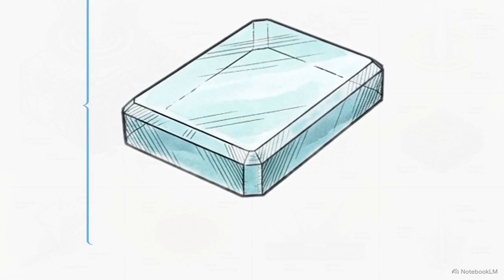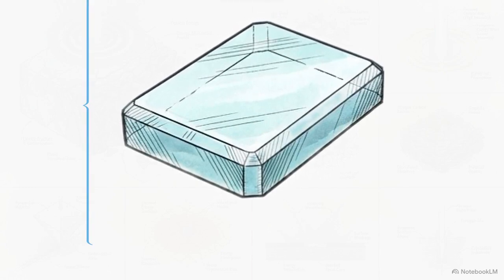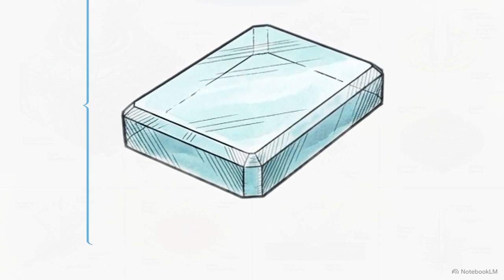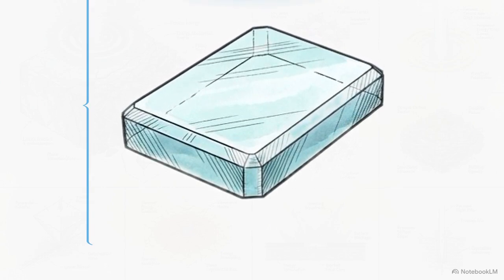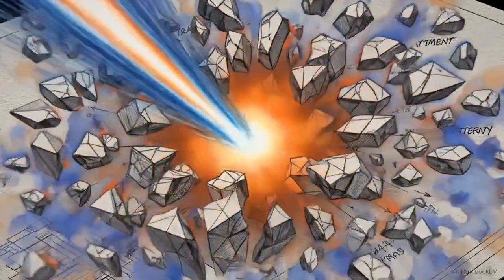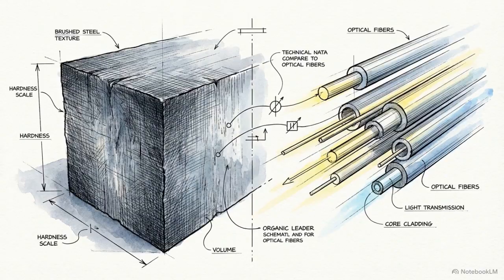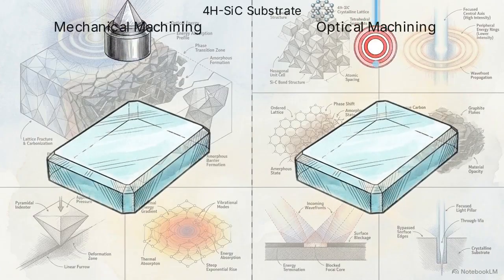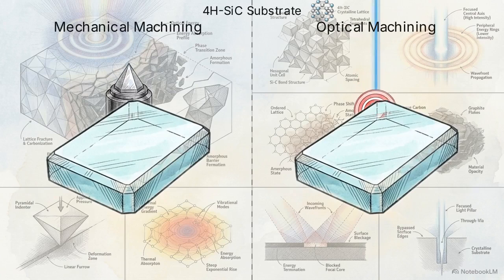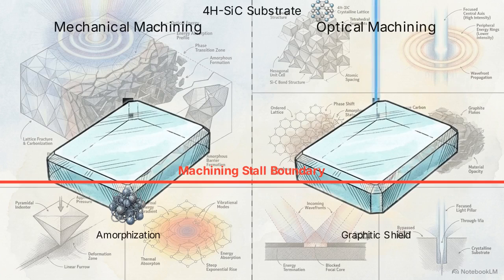Dry etching methods using fluorine or chlorine plasmas are remarkably slow, removing only 0.2 to 1.3 micrometers of material per minute. Consequently, the industry relies on aggressive mechanical machining and nanosecond laser ablation, driving the material to its physical breaking point. Engineers utilize two different ways to force material removal: applying non-hydrostatic mechanical pressure with a sliding indenter, or delivering high thermal loads via a nanosecond laser. Despite the different physics, kinetic versus optical, both methods stall when attempting to create deep, narrow channels.